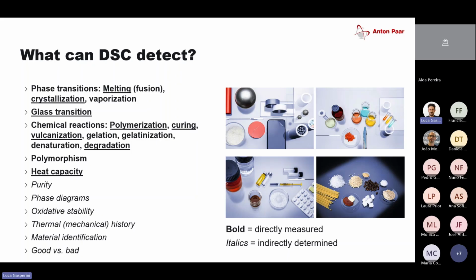The DSC can also be used to identify materials, but not exactly in the same way as you've seen with the FTIR. With the DSC, we usually measure, and by looking at which temperature we see the glass transition of a polymer, at which temperature we see the polymer melt, and how strong this melting process is, we can assess what kind of polymer we're actually dealing with. And as you've seen with other techniques as well, we can determine good sample versus bad sample, because if we compare two DSC spectra, we again might find some differences that give us some information on how the final product should or should not be behaving.